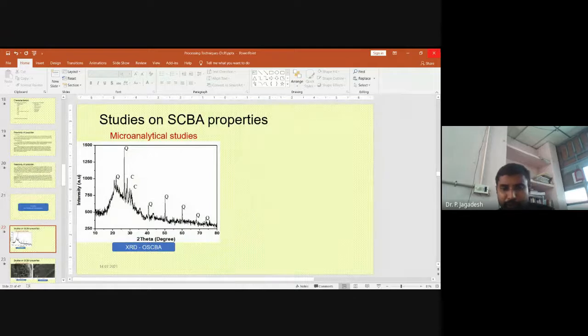This graph indicates the original sugarcane bagasse ash obtained directly from the industry. You can see a large amount of quartz and cristobalite compounds. The cristobalite peaks appear between 27 and 30 degrees 2 theta, which indicates that this cristobalite form is crystalline in nature, an unreactive phase. Quartz is also available, which again is crystalline in nature.